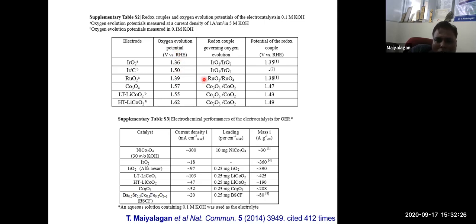evolution reaction. So these redox couples, when you take iridium oxide, ruthenium oxide, versus RHE, reversible hydrogen electrode, it's 1.36. When you take cobalt oxide, 1.57, so very high, and when you take low temperature lithium cobalt oxide, it's 1.55. So these also have redox couples, which help in the potential of the redox couple, which helps in having a better catalyst.